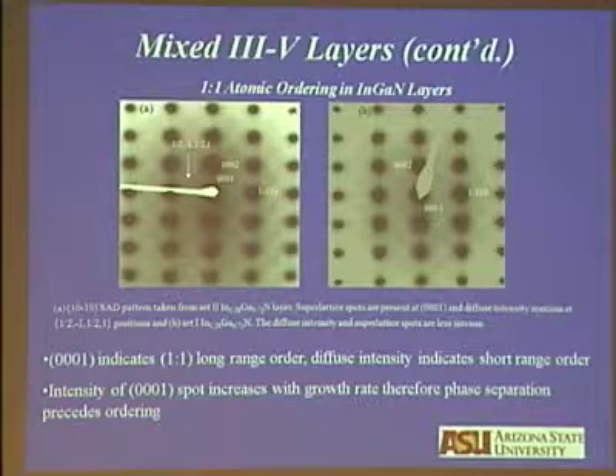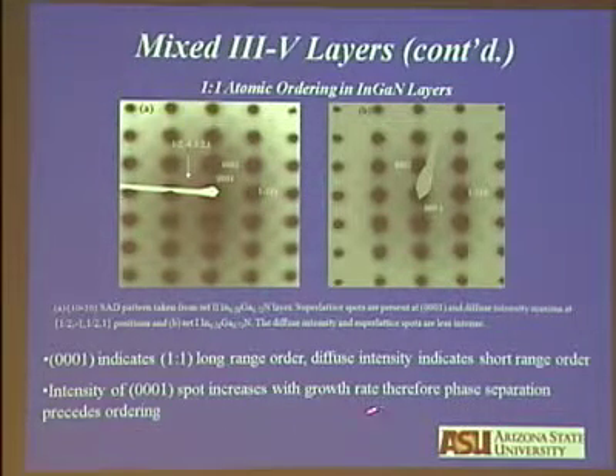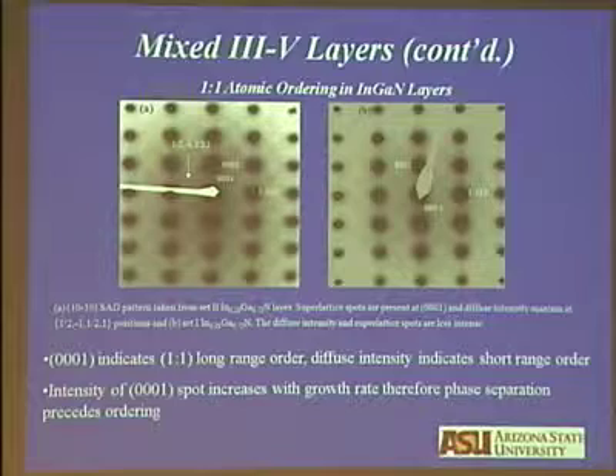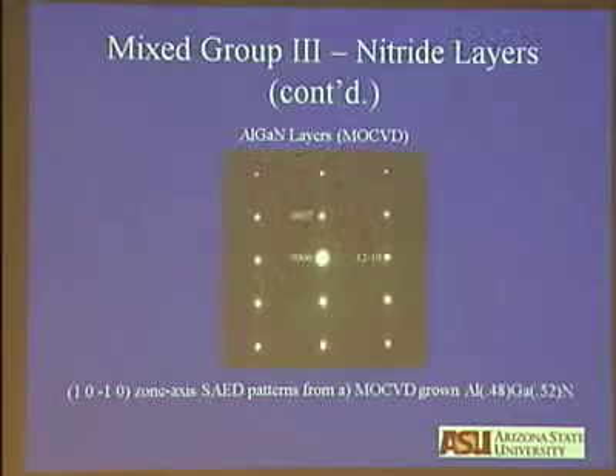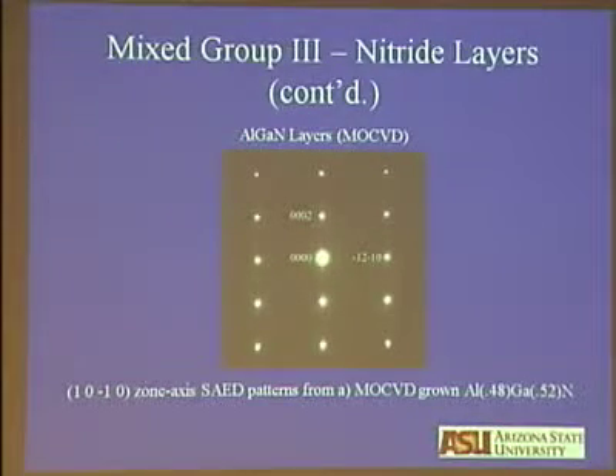And the conclusion, I think I can't develop on that because of time constraint. You see the same thing in aluminum gallium nitride. You get spots and diffuse intensity along the 0-0-0-1 spot. You see that. You get the ordering on that in those.